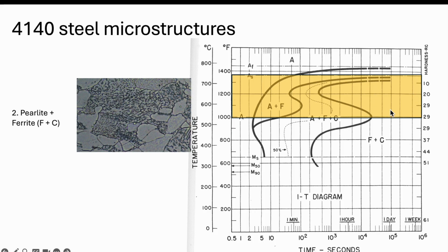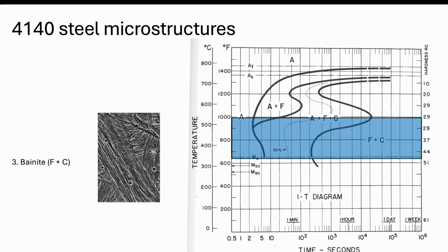One other thing to note, in this TTT diagram, you'll note that it has what we would refer to as a double C or a C shape. So here's a C shape, and then here's another C shape. So the band of pearlite is from this top C, from about 700 down to 550. That means that as we go lower, below that nose here in the middle, we're going to get a different type of microstructure.